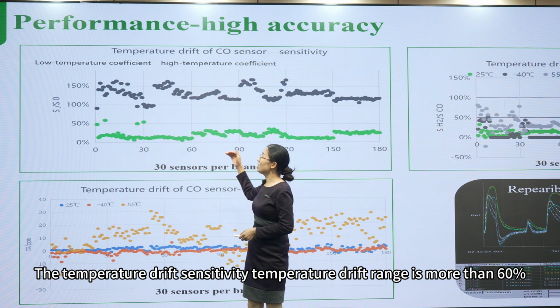And this is the drift of the offset. For the offset, when we use a sensor, the current is detected by the PCBA. If the offset of the sensor is, for some of them minus and some of them positive, we cannot do a compensation, because the PCBA cannot judge whether it is the offset or there is carbon monoxide. So we usually adjust the offset to positive. When the offset is low, it can give us accurate compensation.